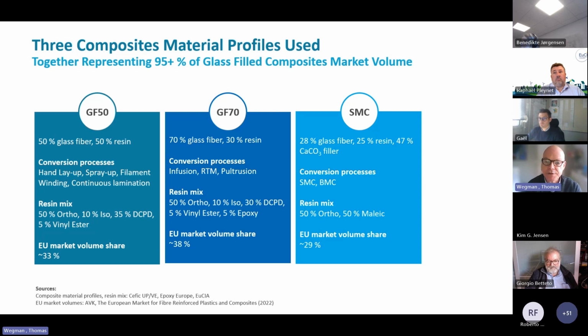The big difference here is that the calcium carbonate filler in SMC has to be converted into calcium oxide in the manufacturing process of the cement. In the typical process of cement manufacturing, calcium carbonate limestone is converted into calcium oxide, which is a key component of the cement clinker. And in that reaction, CO2 is released, which is one of the sources of CO2, besides the CO2 that comes from burning the fuel in that process.